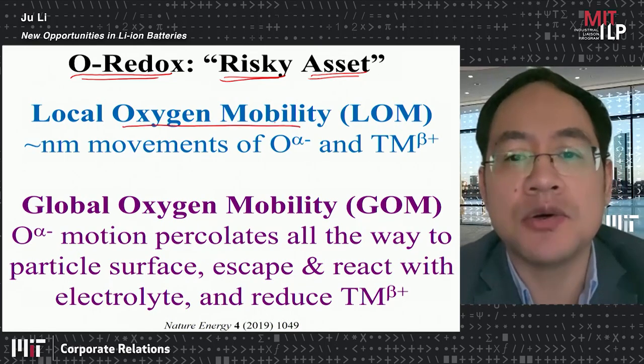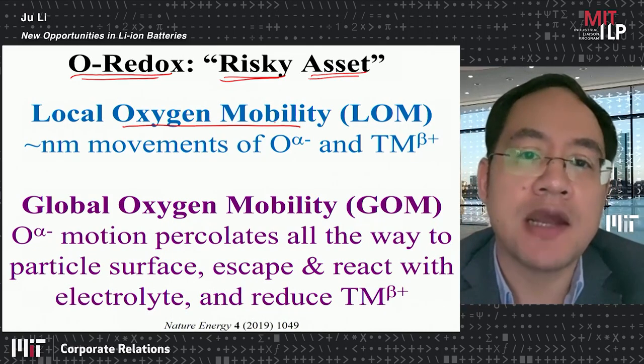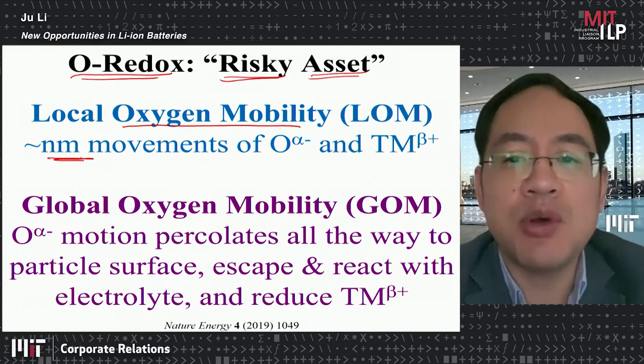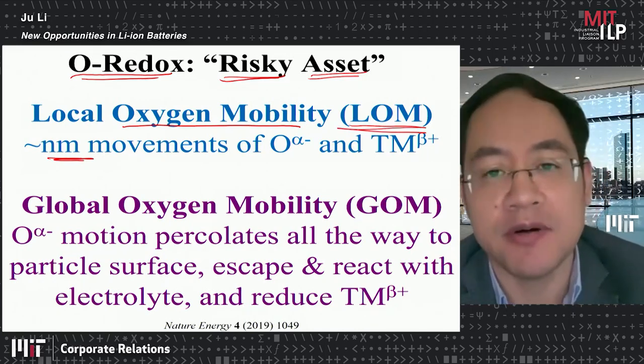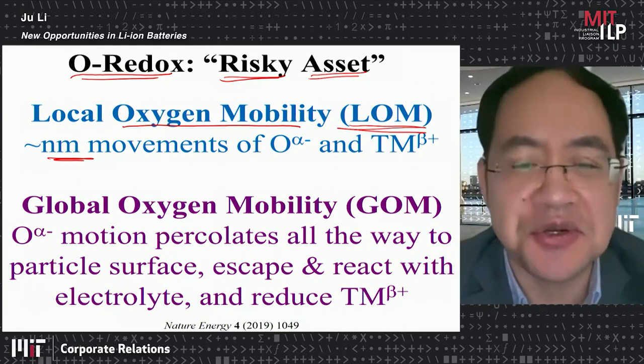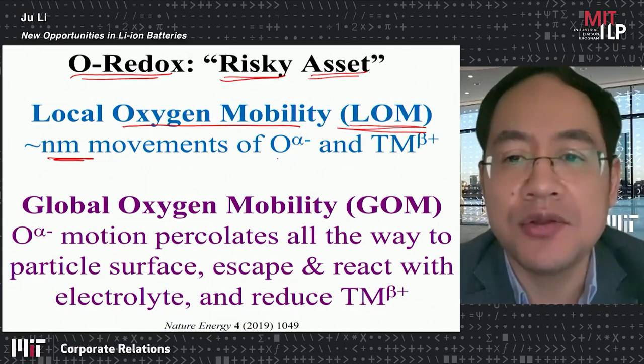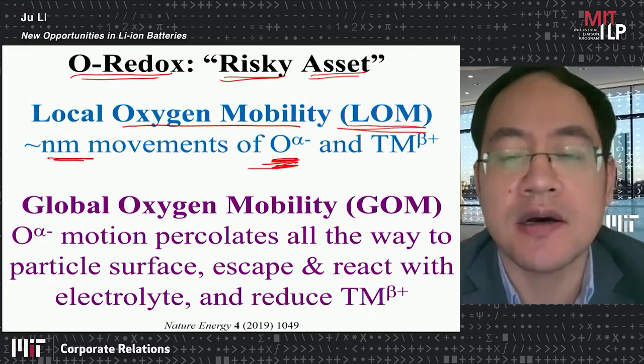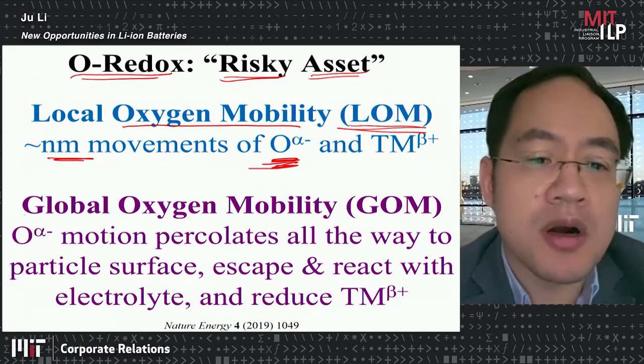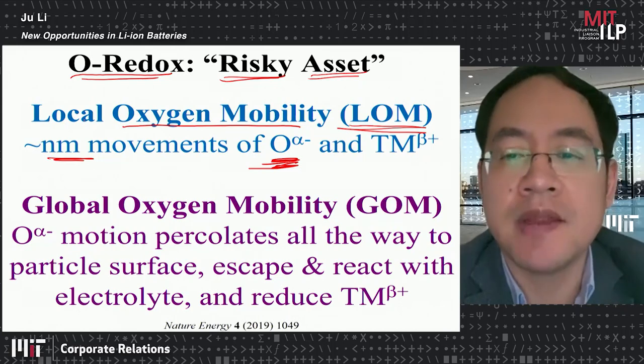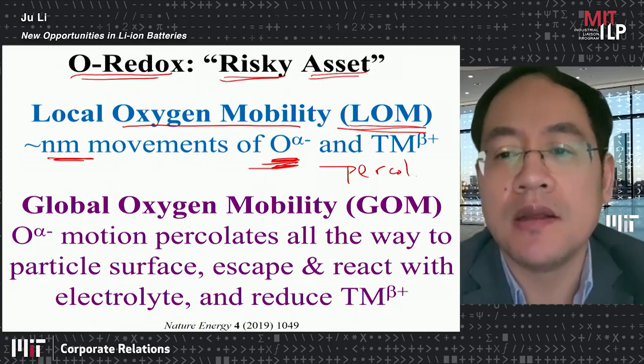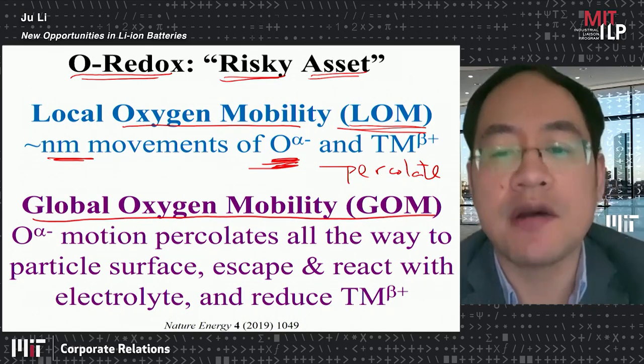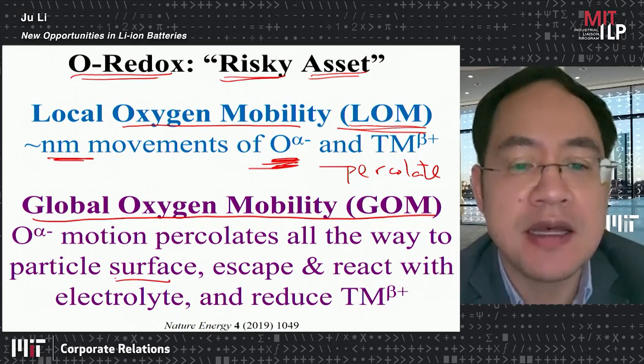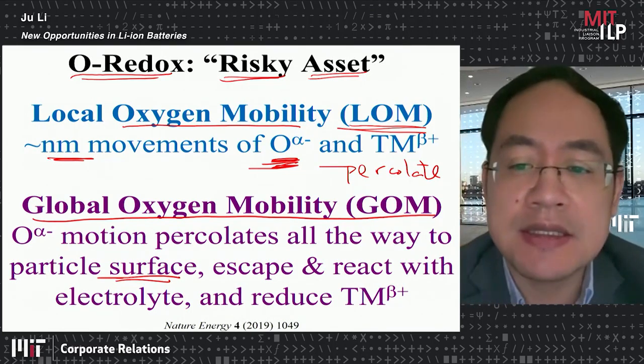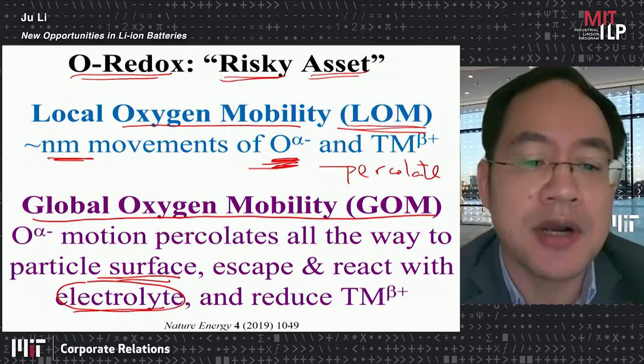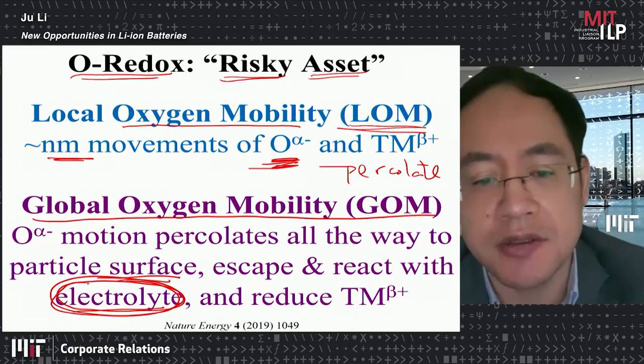When you have oxygen that's going to reconfigure, so it's going to migrate a little bit on the order of nanometers, we believe this local oxygen mobility is unavoidable. It's kind of similar to the situation with sulfur, that you have motion of this oxidized oxide. But the bigger problem is actually if this local oxygen mobility percolates, then you're going to have global oxygen mobility all the way to the surface. And if they go to the surface, they are going to escape and burn your electrolyte. And actually, your electrolyte is the most precious resource in many situations.